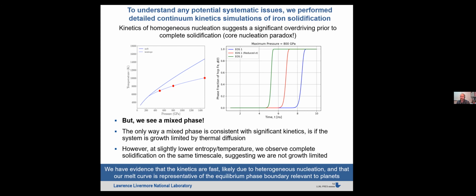So the fact that we observe a mixed phase regime either means that we're observing something close to equilibrium, or that growth into that completely solid state is limited by thermal diffusivity. But the fact that we also now observe complete solidification at lower pressures means we're not in a thermal diffusion limited regime. And again, this mixed phase data tells us that we're observing near equilibrium solidification. When we looked into that in a bit more detail, the equations controlling the solidification timescale are extremely sensitive both to temperature and to the surface energy, where even though this is 4 nines iron, there are a little bit of impurities in there which can dramatically lower the surface energy. So it's the fact that it's not 100% pure, and we're at pressures or temperatures of 6,000 to 10,000 degrees, which is giving us this capability to study equilibrium solidification.